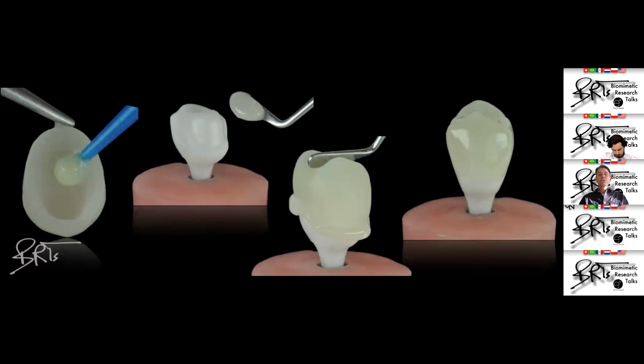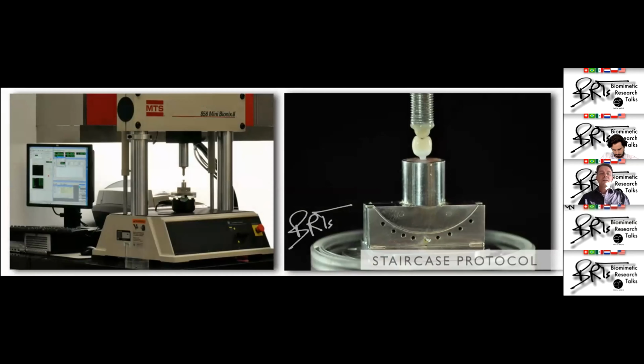So we went to the MTS machine, and following the staircase protocol, we loaded all samples. Different from Elisa's presentation on the anteriors, we went with higher loads in the posteriors. We went up to 1,400 newtons, while on the anteriors we used about 140 newtons. In this case, the loading takes about 8 to 10 hours.